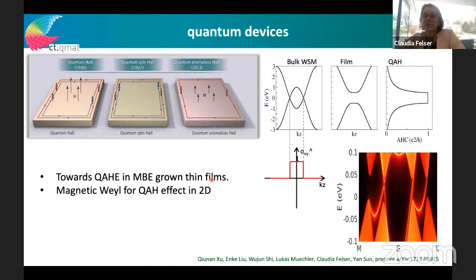So we are looking for the quantum anomalous Hall effect in this material, and we even did a toy model calculation here with a tight binding model. So we looked at what happens in a semimetal if I go really to one layer, a thin film, and indeed this turns a magnetic Weyl semimetal into a quantum anomalous Hall system. And we did some surface calculation of Co3Sn2S2, one layer, and indeed we see some interesting edge states in this material.